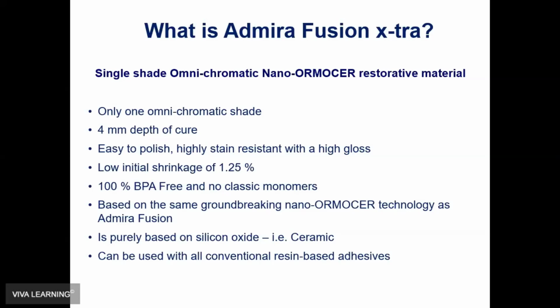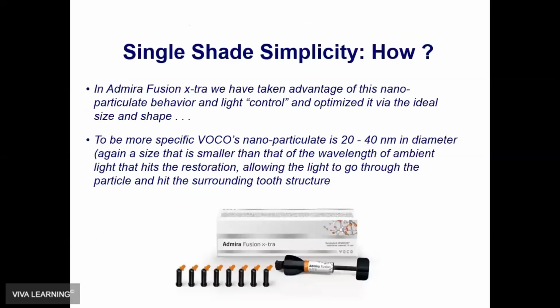You can use it with all adhesives, and it goes to a 4 millimeter depth of cure, which is, if you want an injection mold, you certainly can do this, or if you want a bulk fill, you can bulk fill to 4 millimeters, and it becomes aesthetic by inheriting the color and the environment that you adhere it to.